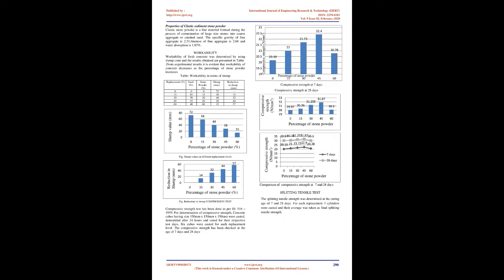Design concrete mix M25 of ratio 1:1.79:2.37, as per IS 10262:2009, was investigated adopting a water-cement ratio of 0.45. For the production of concrete, materials used were ordinary Portland cement 43 grade, natural river sand as fine aggregate, coarse aggregate, sandstone powder as replacement of natural river sand, and potable water. The maximum size of crushed aggregate was 20 mm.